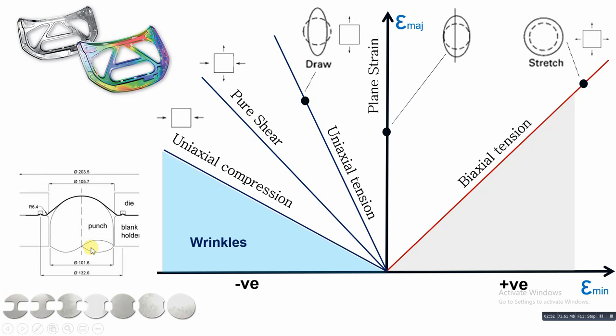those techniques to make or to draw the forming limit diagrams. We repeat the test for each of those specimens three times, and so on, to provoke the material to behave in uniaxial tension here and biaxial tension here, and those points between uniaxial and biaxial located in this region. Okay, after finishing the Nakajima test, we can have here three points. Each point represents a state of stress. This is uniaxial, here is the plane strain, and here is the biaxial tension.